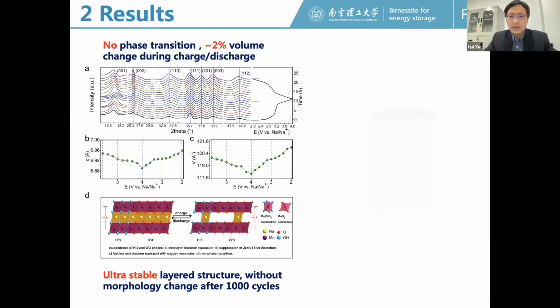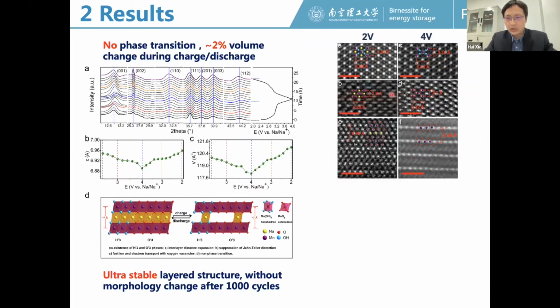And we also did this STEM HAADF image for the fully sodiated state and the fully desodiated state. So we can see actually this structure has negligible change between the charge and the discharge. And especially for this interlayer distance, we can see it only changes slightly between the fully sodiated state and the fully desodiated state.